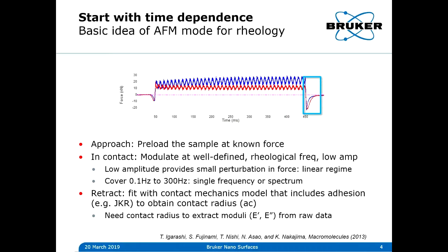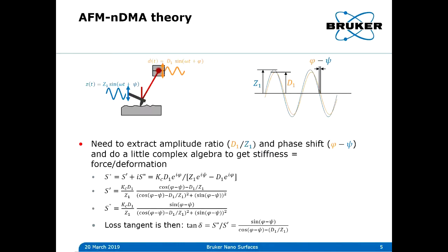I will now describe the analysis of this type of data. If you are familiar with the literature, you may recognize this publication listed below here from Professor Nakajima, one of our collaborators in Japan. So essentially what we want to do here is apply a sinusoidal motion to the Z piezo and measure the motion of the tip. And that will give us an amplitude ratio, a ratio between the amplitude of the Z motion and that of the deflection, and a phase shift between that Z piezo motion and the deflection signal.